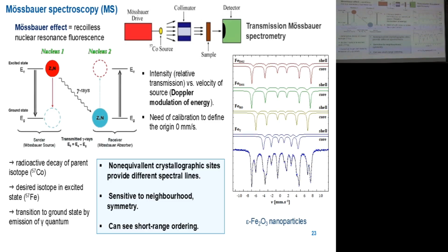And moreover, the sample is based on nanoparticles, and the core is quite well crystallized and magnetically well ordered, but the shell on the surface is typically slightly disordered, and the magnetic ordering is suppressed there. So there are other effects which make it different. So we should separate also the surface volume into separate components. Actually, in this case we did analysis with 8 components separating the core and shell. And if you manage the analysis, the fitting, you can collect information regarding the individual iron sites.